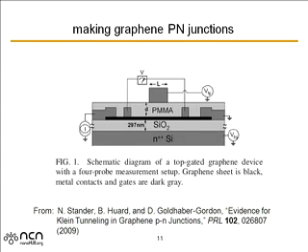ultimately a manufacturable way, but it's a way that you can study the effects and do the experiments and see what's there. So the way these are made is, we have a heavily doped silicon wafer. We're going to use this as a backgate. We just apply a potential to it. There is a layer of SiO2. You can see it's 297 nanometers. People like to use about 300 nanometers so that you can optically see one monolayer of graphene.